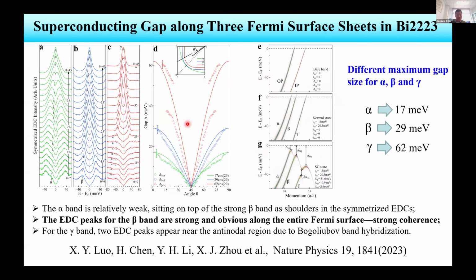Also, we measured the superconducting gap along the three Fermi surface sheets. We have alpha, beta, and gamma, and we can see that the gamma Fermi surface has the largest superconducting gap. It reaches about 60 millivolts. But the alpha and beta Fermi surfaces have a smaller gap, around 20 to 30 millivolts. So we have different gap sizes along different Fermi surface sheets, but gamma has the largest gap.